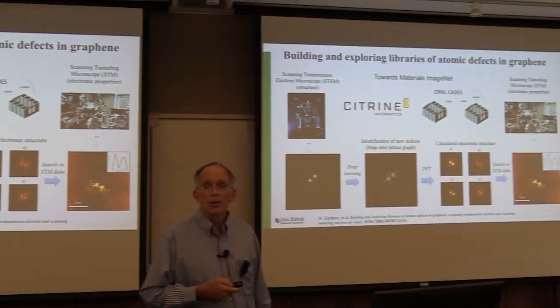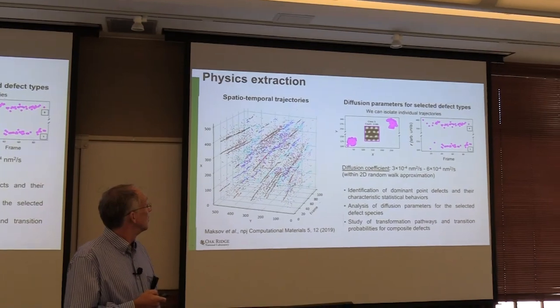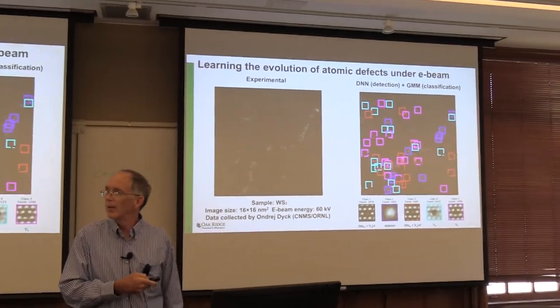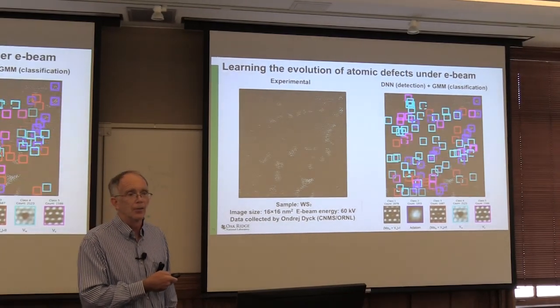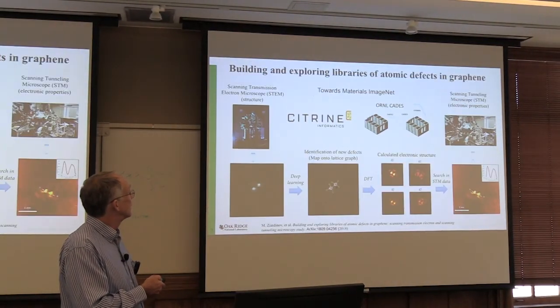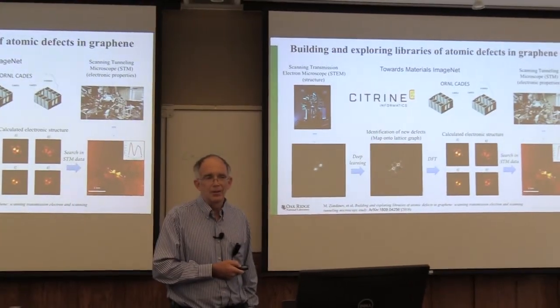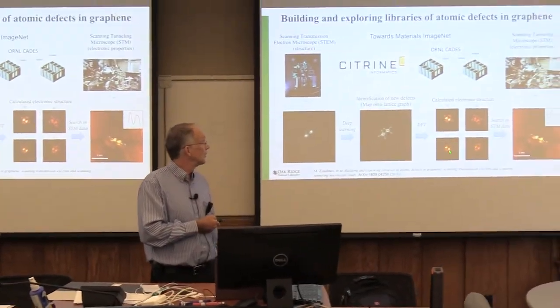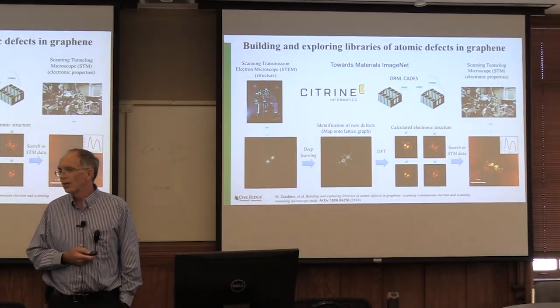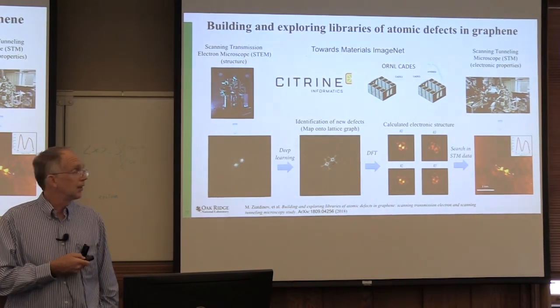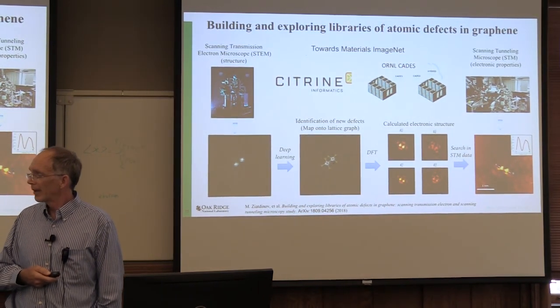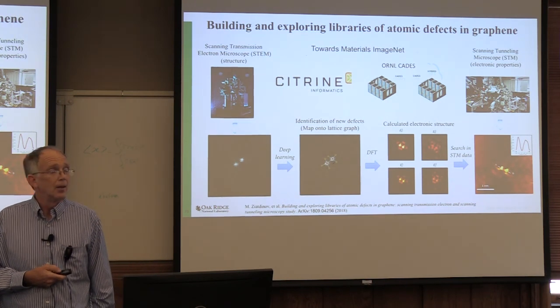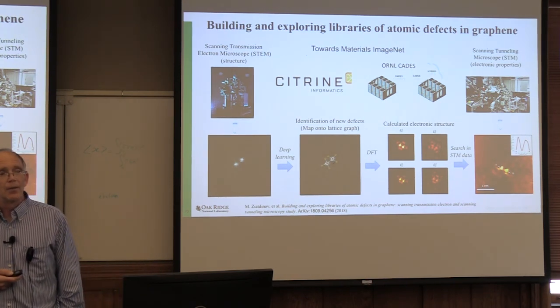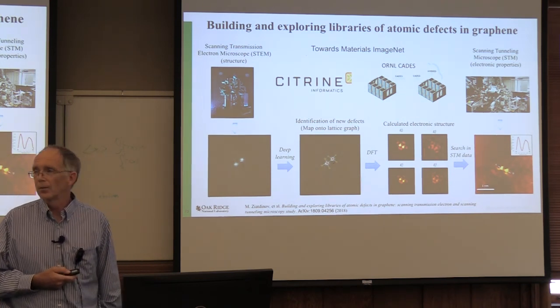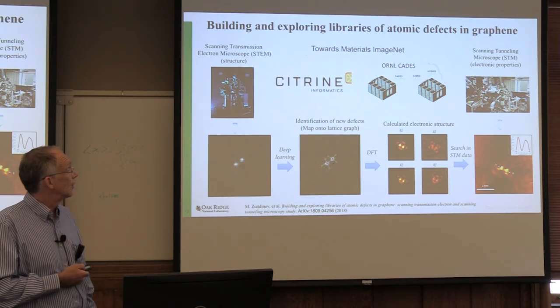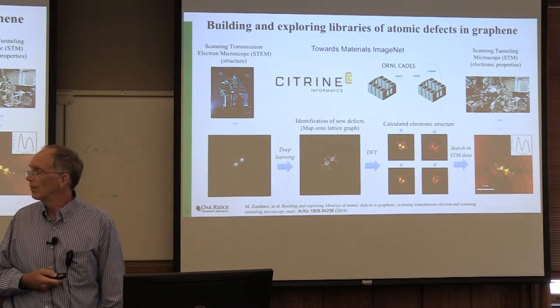We're now including not just electron microscopy, but you could ask the same questions: what would a scanning probe, STM or AFM, look like? It's a little cheaper than $4 million to do STM or AFM. So we don't have to do experiments, because to be honest, we can do calculations. What we did in the STM cases was density functional theory calculations of all those defects, and projected out what they should look like, and let the neural network learn from the calculations instead of experiments. You don't have to use experiments. And now we populate the database with defects, both for scanning transmission electron microscopes and scanning tunneling microscopes, so that one can access that information for these materials.